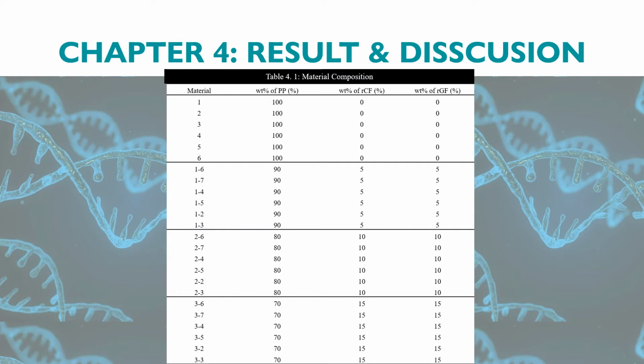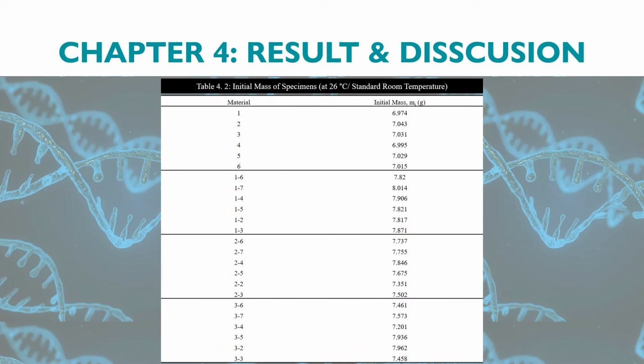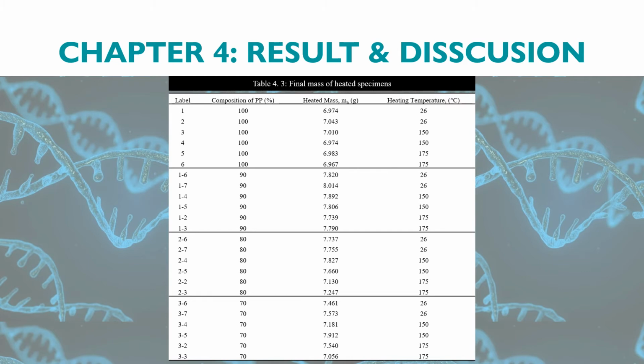For the second test, which was heating using an oven for 1 hour, there were 3 different temperatures: 26 degrees at room temperature, 150 degrees, and 175 degrees. Table 4.2 shows the initial mass for every composition ratio. As the heating took place, the result in every composition ratio shows rapid degradation as the temperature increased from room temperature to 150 and finally to 175. Comparing the composition of carbon fiber and glass fiber, the degradation at the same temperature increases when both materials increase in content. This might be because of inconsistency of thermal loading in the structure. Hence, rapid degradation happened in the polypropylene.